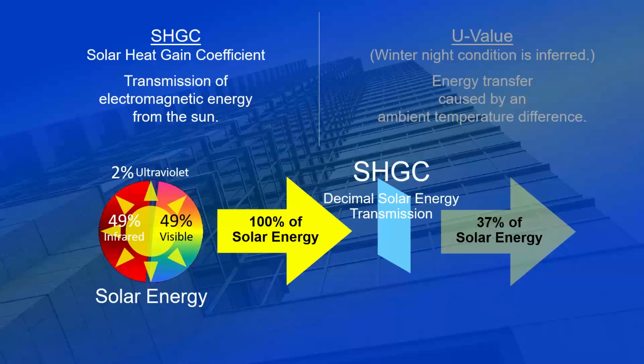For those that have been in the industry for a while, you may be familiar with shading coefficient. We still often see shading coefficient listed in specifications. The difference is that shading coefficient is calibrated to the solar energy transmission of 1/8 inch thick or 3 millimeter glass, which has a shading coefficient of 1.0. Solar heat gain coefficient is not calibrated to a physical sample, but rather is the direct and indirect solar energy transmission represented in decimal form.